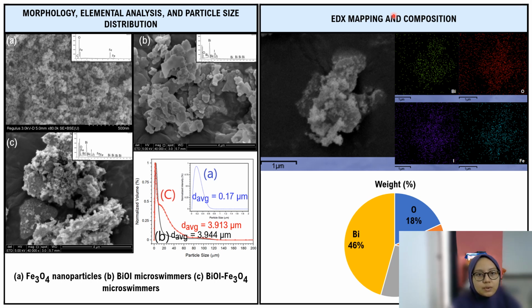This figure shows the EDX mapping and composition of the bismuth magnetic microswimmers. It can be observed that each of the elements is well distributed, with the highest composition of bismuth followed by iodine and oxygen. The lowest composition is iron.